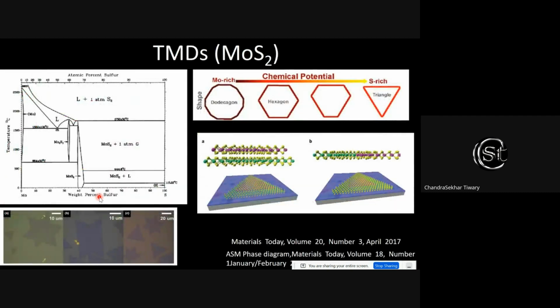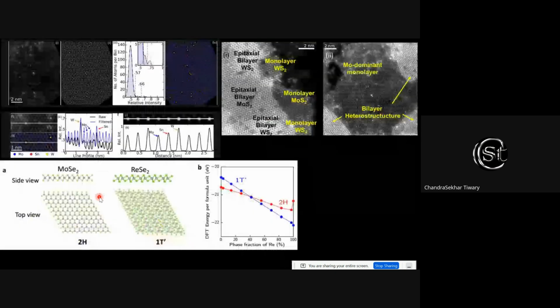Moving next, in this atomically thin material, MoS2 has become one of the popular materials for several applications, lubrication and all. Again, this is more related to electronics grade, where people can modify the structure and hence change the electronics. I'll not discuss this in detail, but just to tell you, in this atomically thin material, the interesting part is here. What you see on top is the structure from the transmission electron microscope, and any bright spot is a different atom in this 2D material.